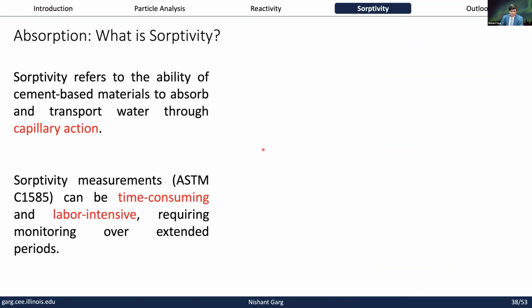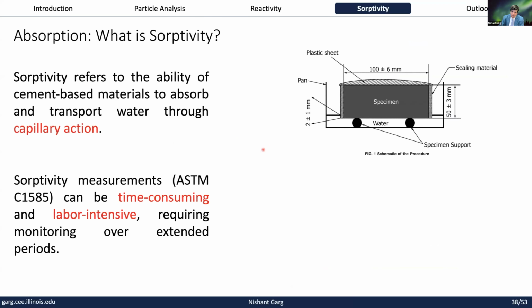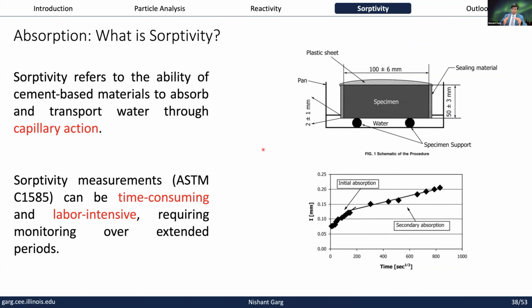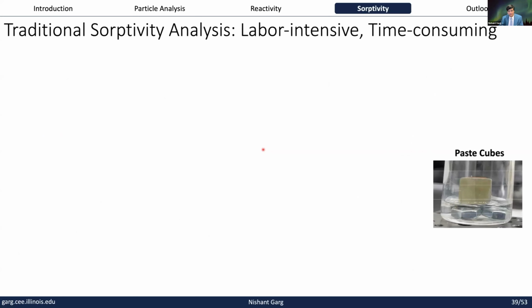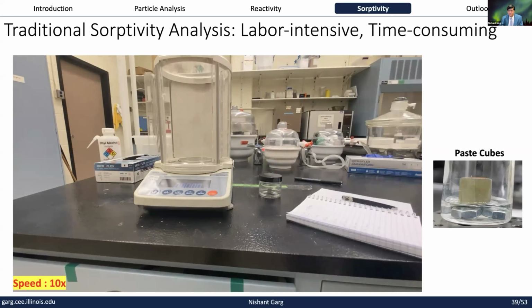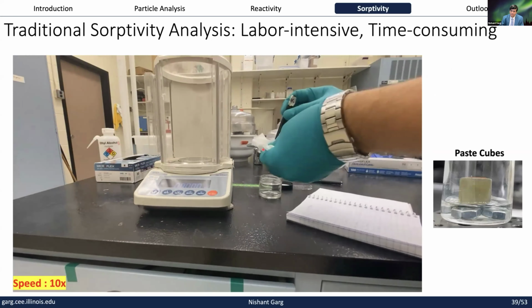Now, there is a very nice ASTM standard for these sorptivity measurements. However, it's a little bit time consuming and labor intensive. Essentially, you have this specimen which you expose to water from one end, and you repeatedly measure its weight over time to build a penetration curve, the slope of which can tell us how rapidly the water is moving in. So here's a little video of that test done on cementitious paste samples.